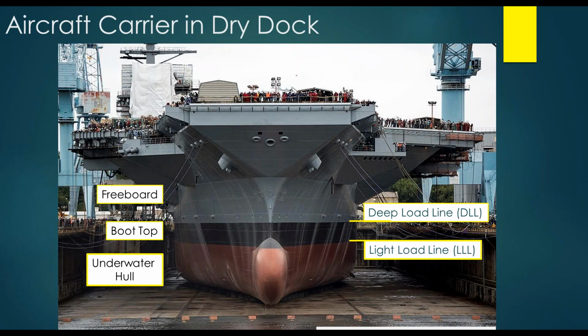The coating systems used on an aircraft carrier vary according to the anticipated exposure environment. For instance, the freeboard is the part of the hull that is above the immersion line. Similarly, the underwater hull is that portion of the hull we would expect to be continuously immersed. The boot top is the part of the hull that will have varying degrees of immersion depending on the loading in the boat. The light load line is where the ship should sit in water when it is unloaded. And the deep load line is the deepest that the ship can safely rest in the water until buoyancy becomes a concern.